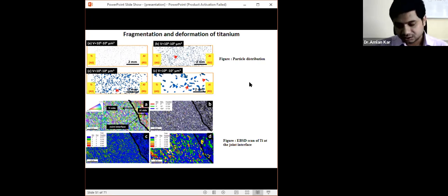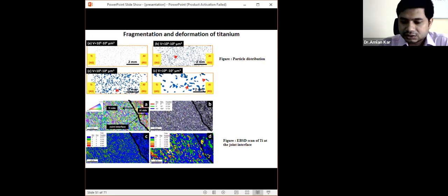So the important factor is how these particles are forming, because the objective is to get nano size particles, and we can see that the coarse particle is subjected to fragmentation in certain locations. So what is the mechanism by which the particle is subjected to fragmentation? For that we have characterized the titanium, and we have seen that there is recrystallization. Recrystallization is a very unusual phenomenon observed in titanium at 450 degrees centigrade.